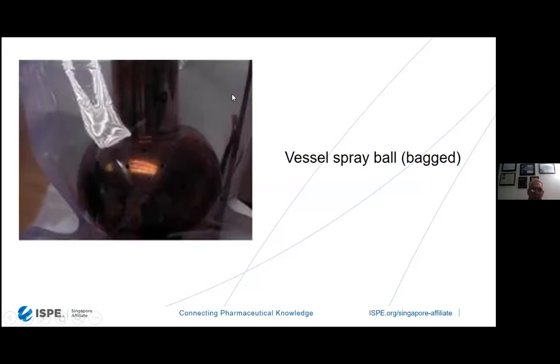And what happened was the QA/QC came in and they felt that they were better engineers than the engineering staff. So they said, we want you to put a bag around your spray ball so that none of this will flake off and get into our water system downstream. But as you can see, that is that black or dark purple rouge, which is an annealing effect. It can't flake off. It can only be removed with phosphoric acid at 80% and 80 degrees Celsius. So the possibility of this actually flaking off is negligible.